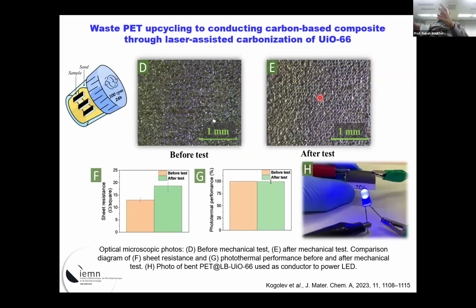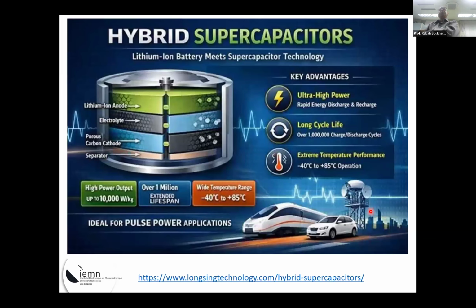Now, mechanically as well, this is really quite stable. We mixed these films with sand, and you can just rotate that over 24 hours, and you can see definitely there's no change in the morphology, neither in the photothermal properties or in the sheet resistance. This is really conducting. This is ongoing work. Now we want to add a solid state electrolyte to make a solid state supercapacitor. I will go for the next 2-3 minutes on what's really going on, and I think that's exactly where the future of the supercapacitors definitely lies.